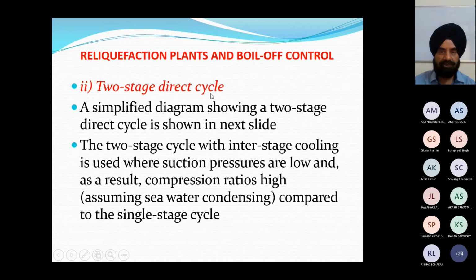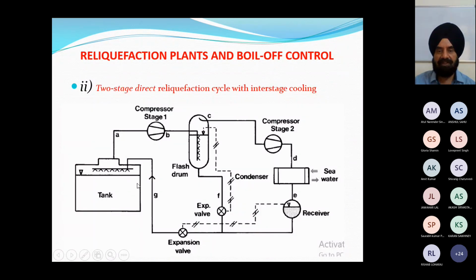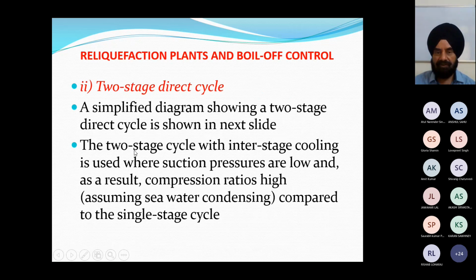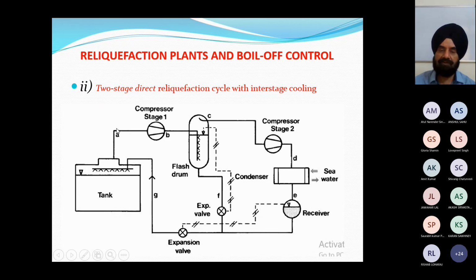Two-stage direct cycle. This is also similar but slightly different. The two-stage cycle with interstage cooling is used where suction pressures are low and as a result compression ratios are high. Here also the same thing: vapors are drawn up to the compressor, then they go to the intercooler, where they are cooled through part of this cargo liquid, and the rest of the liquid goes back. From here the vapors are taken to the stage 2 compressor, where they are again cooled through a seawater cooled condenser, and then as a liquid, part of this liquid goes to cool the intercooler and the rest of the liquid goes back to the tank. So this is the two-stage direct reliquefaction cycle.